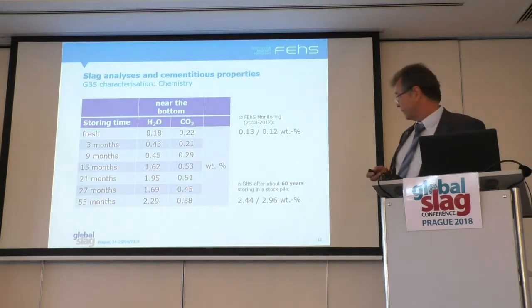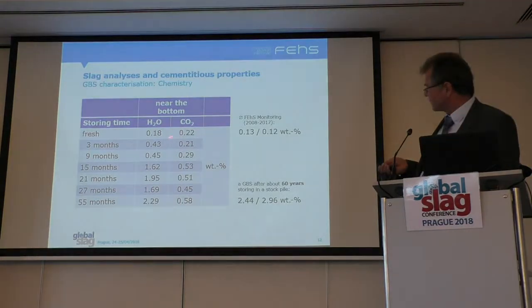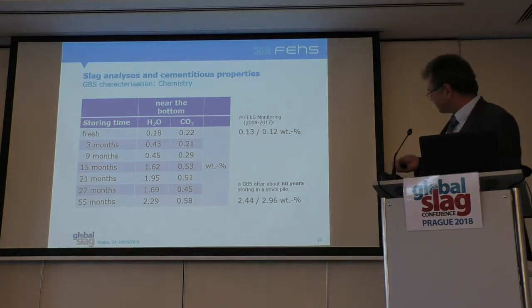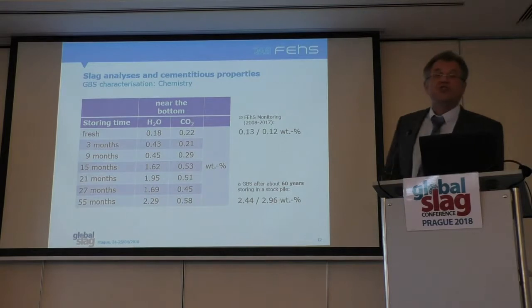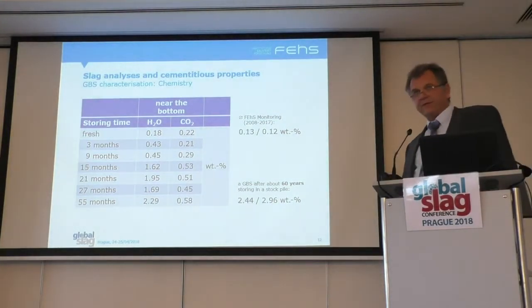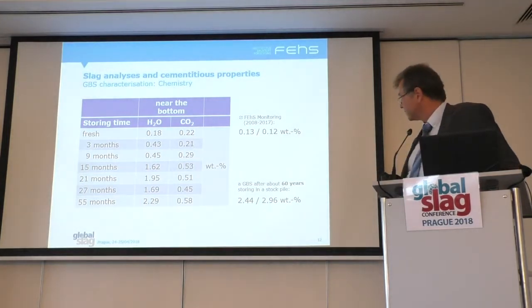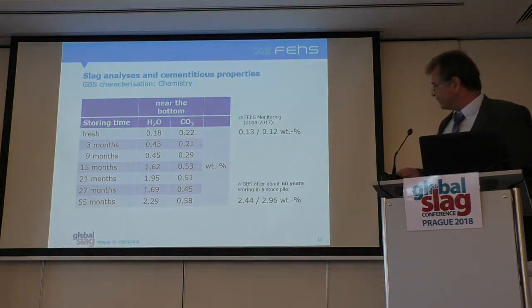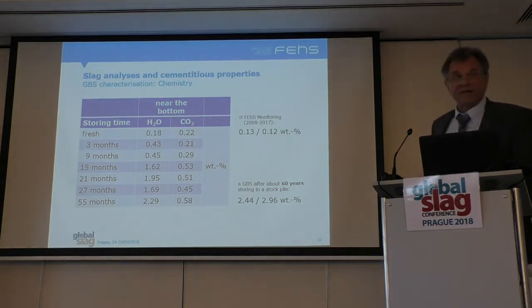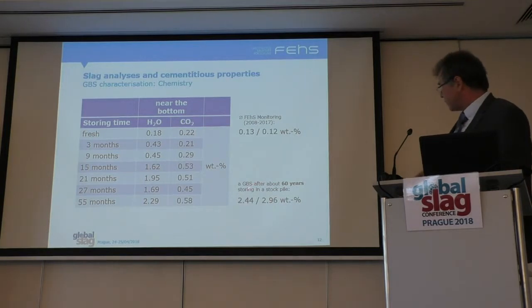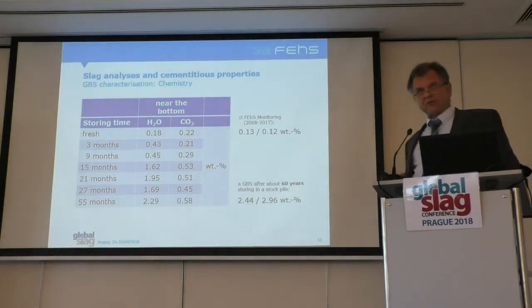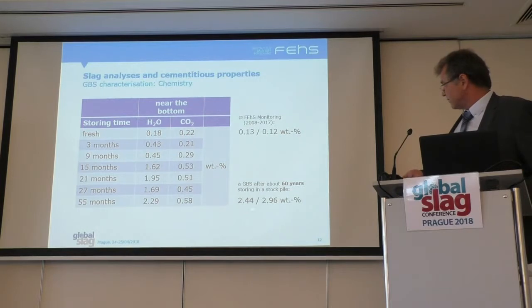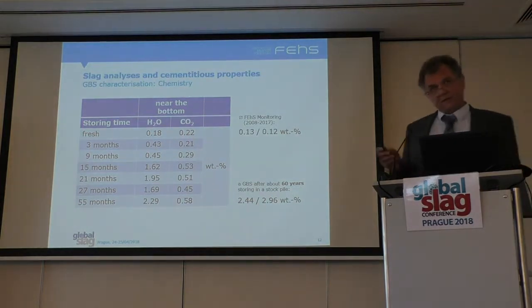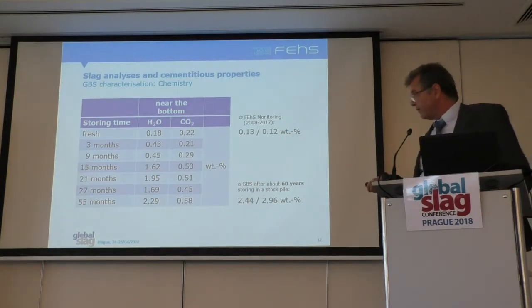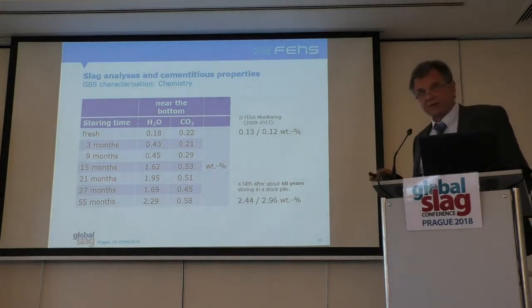bound CO2 is also increasing. If you compare the values of the fresh slag, for example, twice a year we make a GBS monitoring for the members of FEhS, separately for each GBS from single blast furnaces. Very similar values. And to compare the values after 55 months, we wrote here the data for a GBS which got 60 years storage outside. And you see the water content is very similar and the CO2 content is much higher. So we have really the effect of a long storing time in our sample.